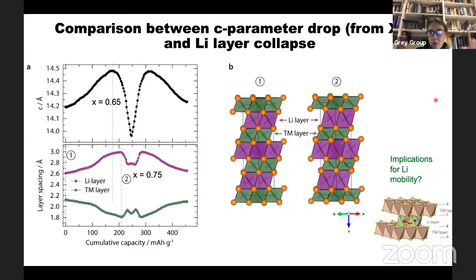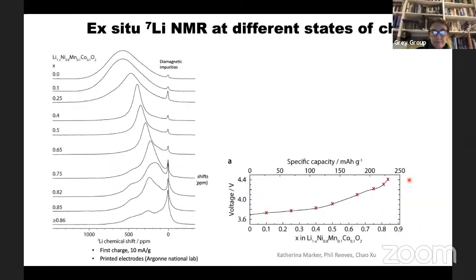So let's think about why this might be important. Here's the layer again. Here's the picture of the expansion and then the collapse. And the collapse occurs at about 0.65. But in point of fact, the actual lithium layer, so this is the lithium layers here, collapses at about 0.75. And so the question is, if the layer collapses, what is the implication for how fast the lithium ions are moving in this structure? And that's obviously important for the rate of the battery.